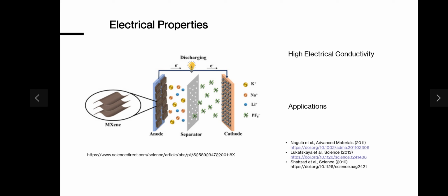Now, carbide sheets also have high electrical conductivity. MXenes like titanium 3 carbide 2 exhibit metallic conductivity with measured values up to 10,000 S per centimeter, among the highest for 2D materials. This conductivity depends on the type of transition metal and the number of layers. Surface terminations, for example, oxygen enhances while fluoride reduces conductivity. The conductivity also depends on the degree of flake alignment and delamination.